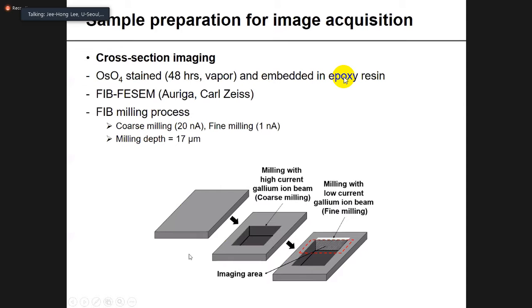For cross-section imaging, FIB-FESEM was utilized, and the coating layers were also osmium tetroxide stained and embedded in epoxy resin. And the FIB milling process was carried out in two stages. First is the coarse milling, and second is the fine milling.